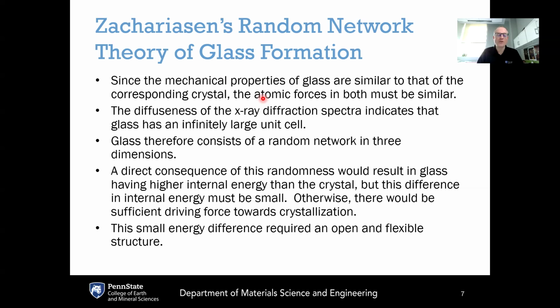And Zachariasen deduced that this bonding between the silicon and the oxygen must be basically the same in a crystal like quartz as it is in vitreous silica or silica glass. Now, Zachariasen was one of the pioneers of using X-ray diffraction to study crystallography. And when Zachariasen used X-ray diffraction to study glasses, what he saw was what we saw in our last lecture, which is this very diffuse so-called amorphous hump coming from XRD.